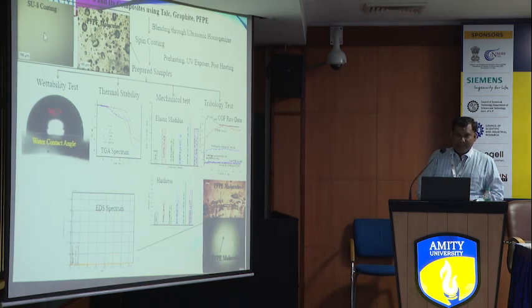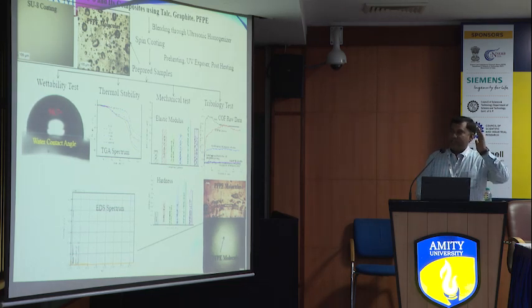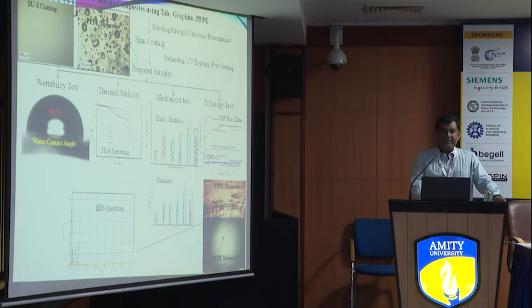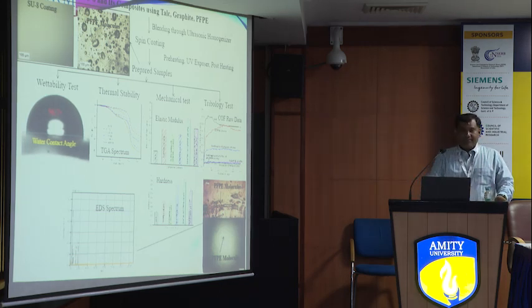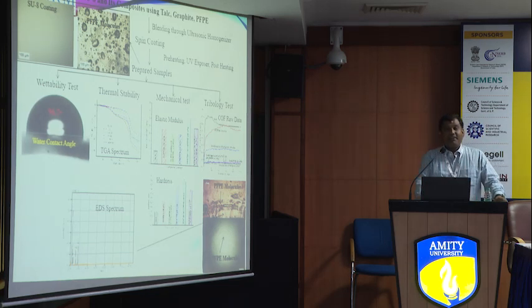see the pure coating, and after adding the filler, simply you can see the droplets of the filler, and that is also throughout the thickness. Thermal stability improved, and elastic modulus and hardness also improved. Coefficient of friction, you can see here, is approximately 0.05. That was a further enhancement in the coefficient of friction.